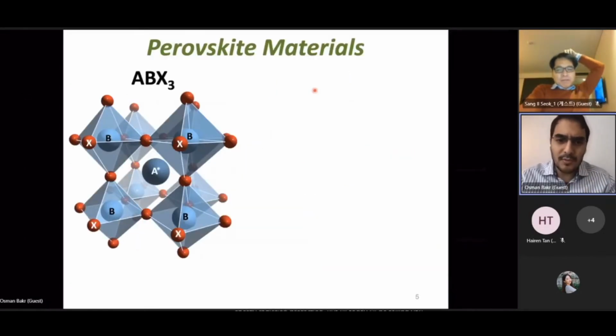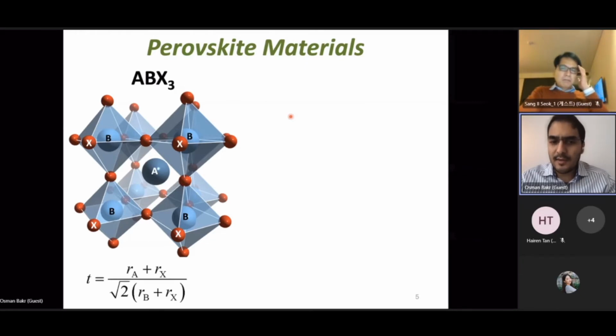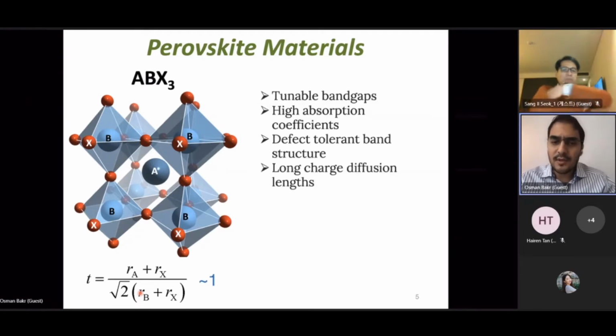And for those of you who are not familiar, perovskites are these ionic compounds that have this ABX3 formula, where B is in an octahedra of X, and A is in a cavity inside, surrounded by BX6 octahedras. And many elements can form this perovskite structure as long as they obey this tolerance factor. And as long as the tolerance factor is close to 1, then a lot of materials do form this structure.